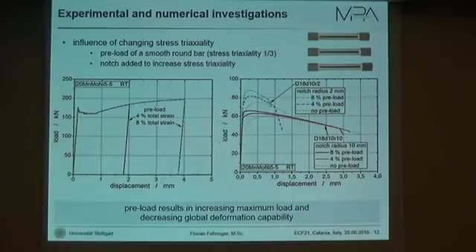And as you can see, with an increasing preload, so we have no preload, 4% preload and 8% preload, we get an increasing maximum load, and which is more important, we have a reduction in the global deformation capability of the material.